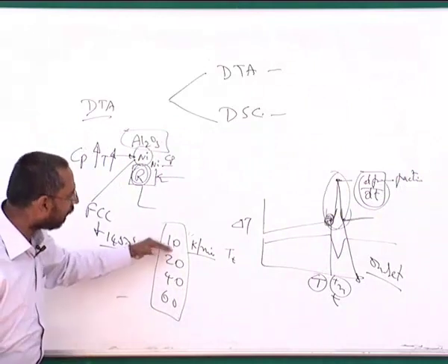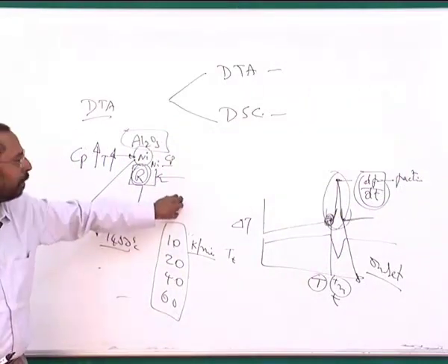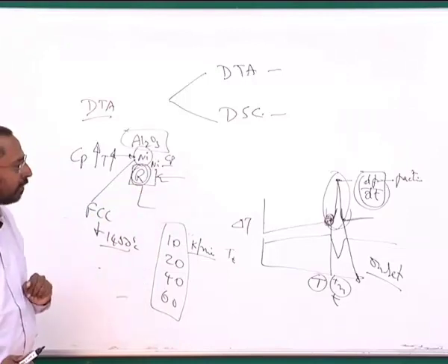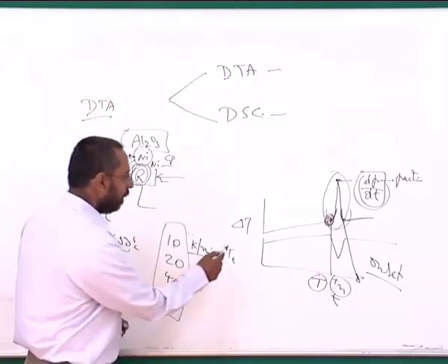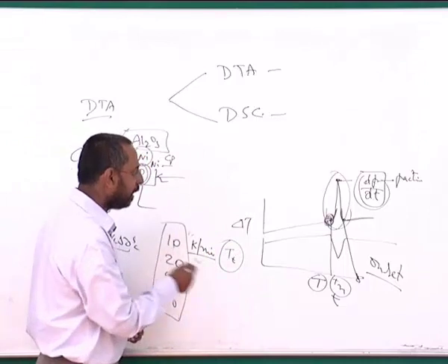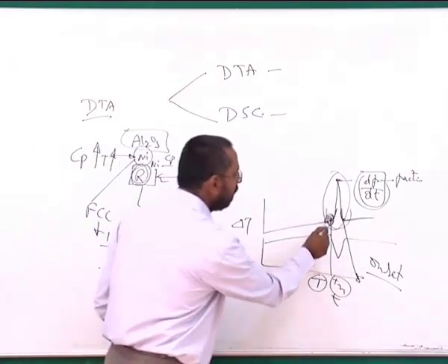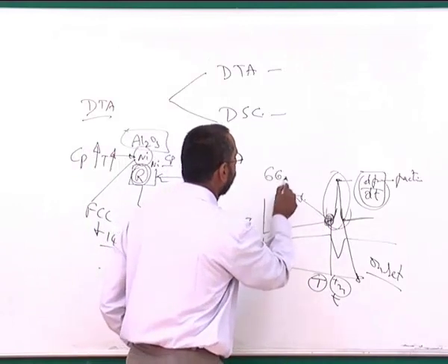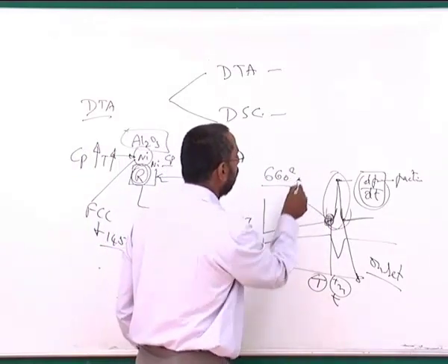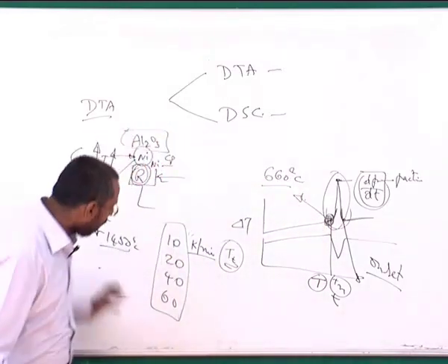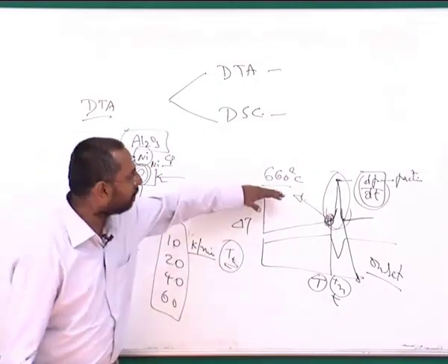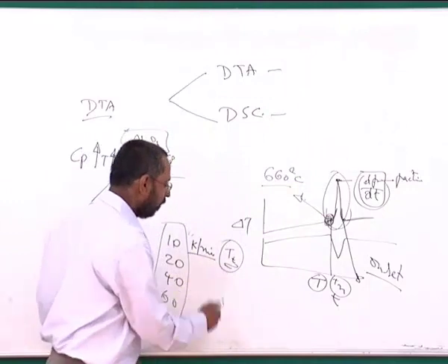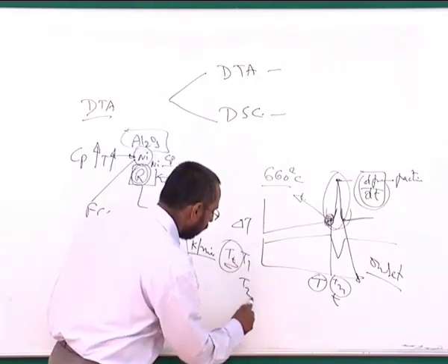So when the heating rate is close to the equilibrium heating rate, which is very close to 0, the actual transformation temperature at that heating rate is the true equilibrium transformation temperature, which, for example for aluminum, let's say is 660 degrees centigrade. If I am heating it faster, it will not be 660, but it will be higher than 660. And if I measure all these, let's say T1, T2, T3, T4,